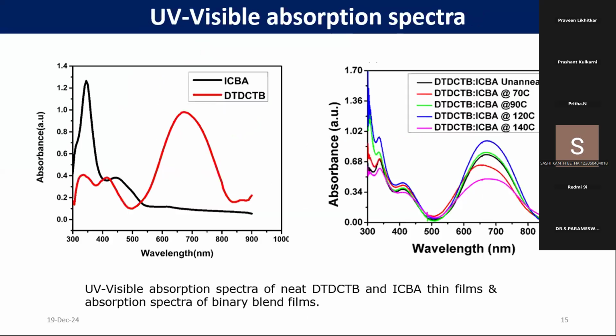So once that has been done, we need to characterize the blend films as well as the devices. So these are the individual thin films, like donor and acceptor. Donor is absorbing from 480 to 880, around 900 nanometers, and acceptor ICBA is absorbing in the lower wavelength region. In that way, it is able to cover the 300 to 900 wavelength region. And if we mix them together, this is how it is able to cover up to 900. So there is an advantage with the mixing of donor and acceptor, and it can form bulk heterojunction structures.